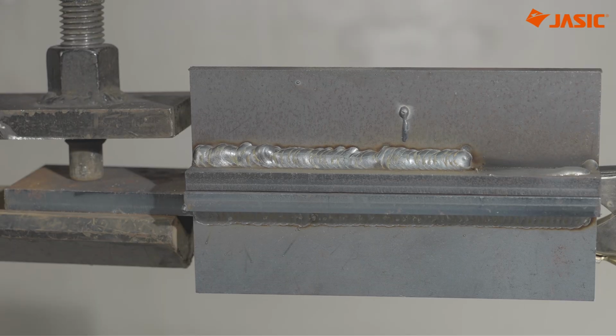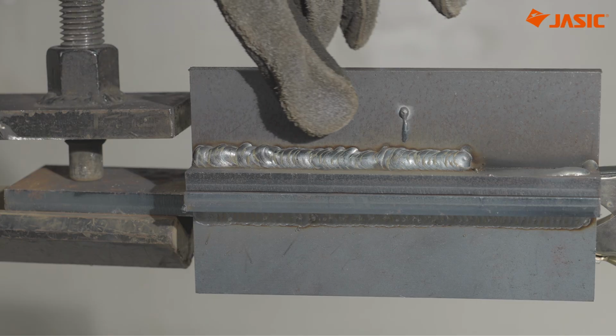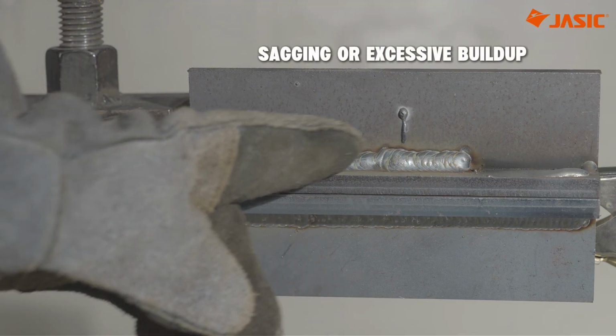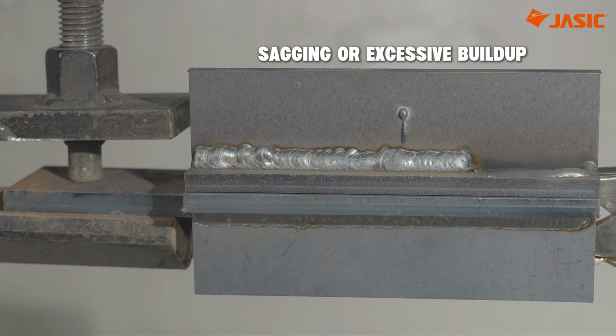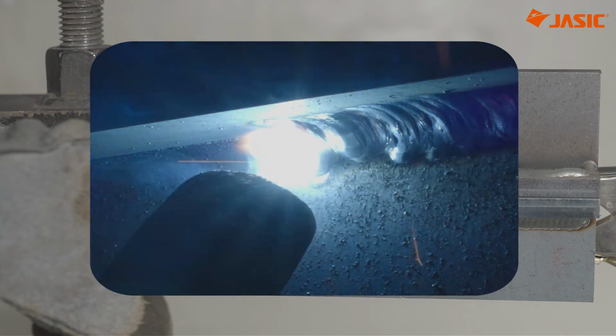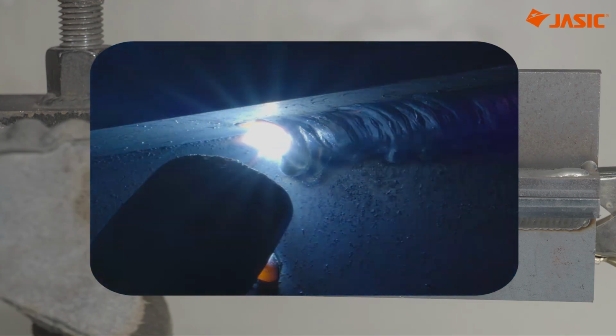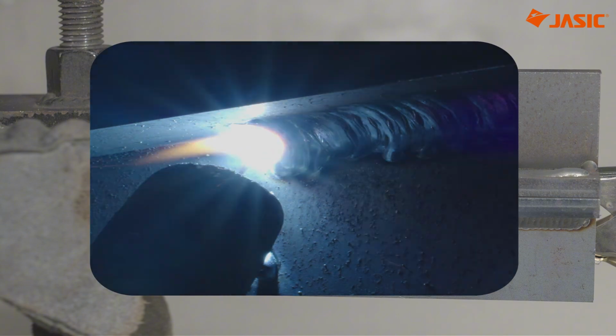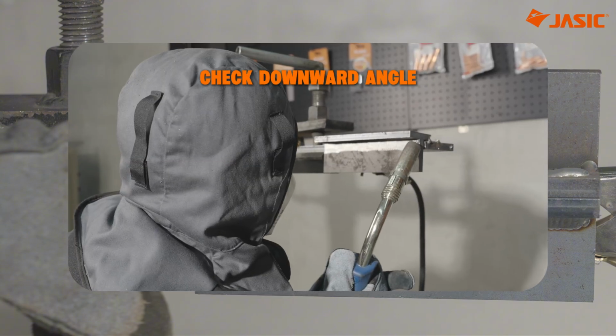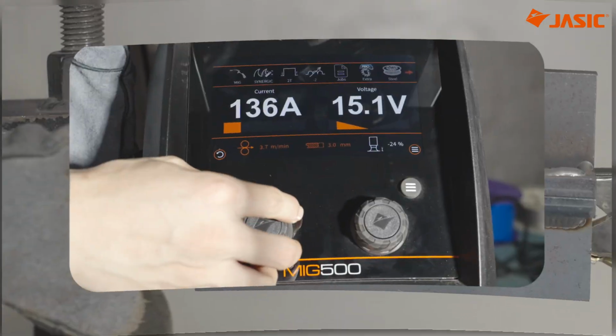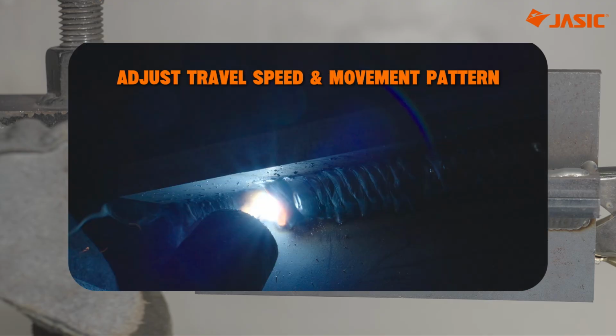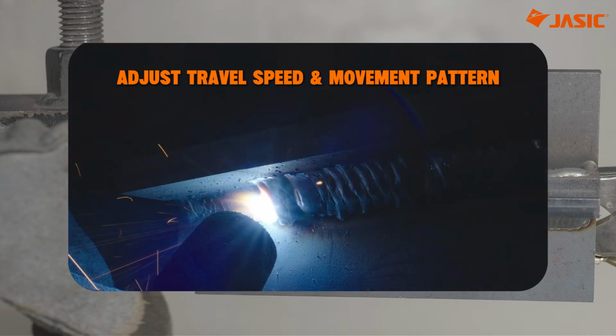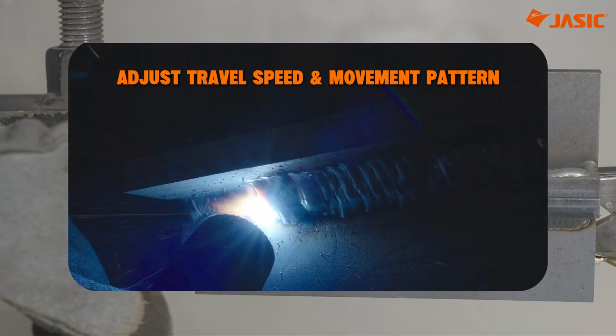Here are some of the most common problems you'll see when overhead welding. Sagging or excessive buildup. This is one of the most typical problems in overhead welding. It usually means the current is too high or your gun angle and travel speed aren't doing enough to counteract gravity. First, check whether you are applying enough downward angle. Then reduce the current if necessary.